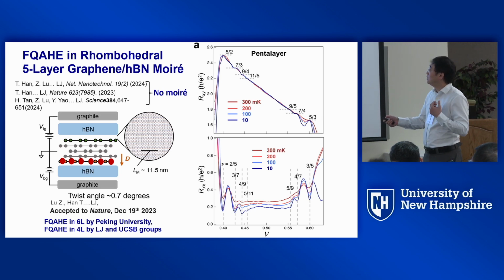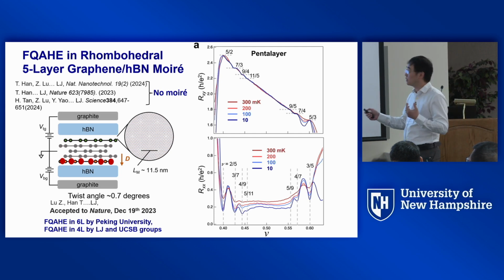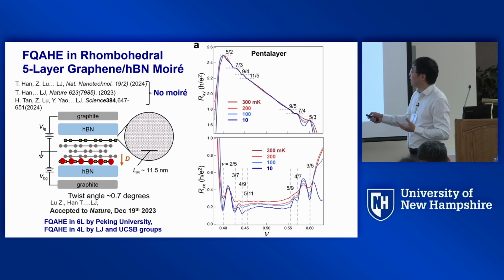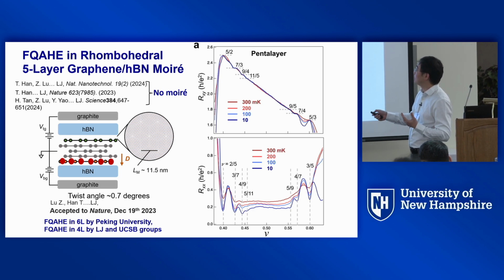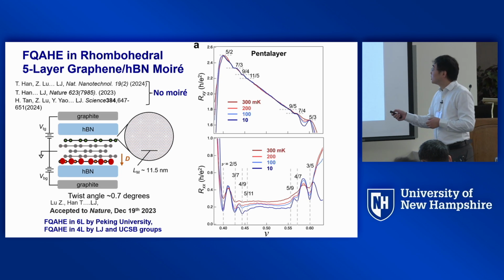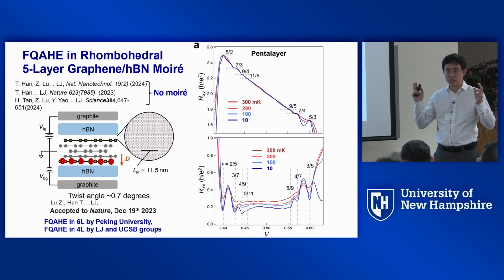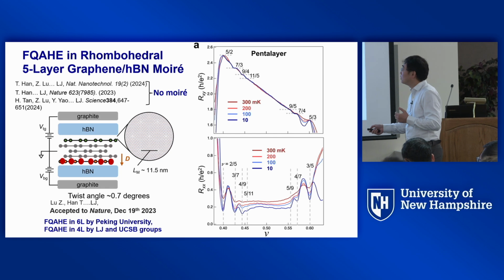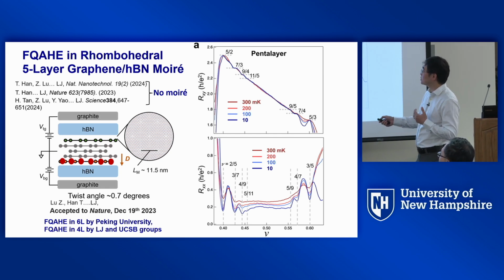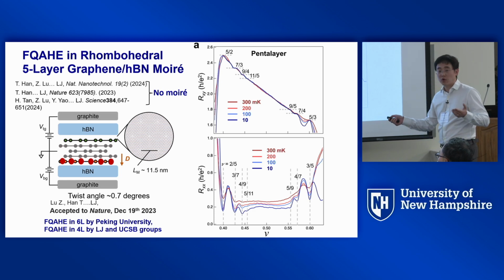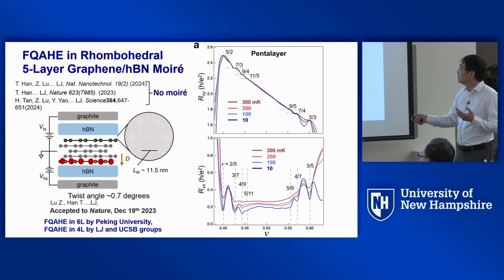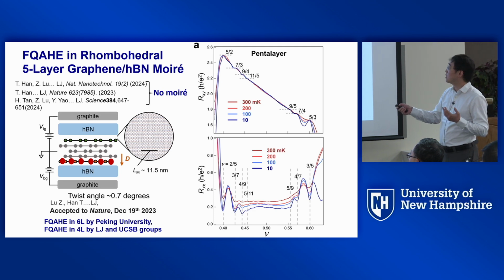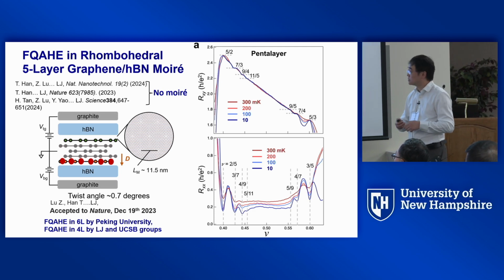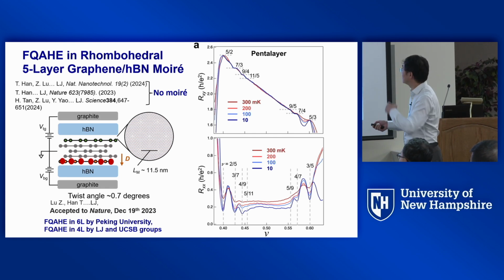And here I'm showing you our early work on 5-layer rhombohedral graphene, ABCAB. Okay? And before we introduced moire, it was already pretty interesting, as we have several works by Tonghang and Zhengguang where we got signatures of correlation and topology in the absence of moire. What probably catches the most attention is when you introduce a moire superlattice between graphene and the hBN with a moire period of something like 12 nanometers, almost 0-degree twisting. You get the so-called fractional quantum anomalous Hall effect that I believe is mentioned by our speakers, and also probably Xiaodong will talk about tomorrow.